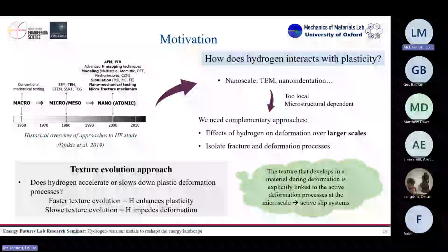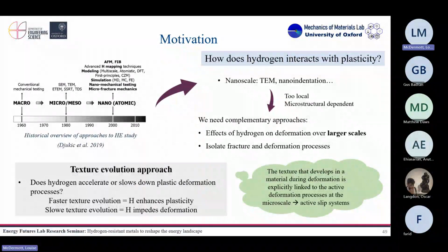So what we could say is, okay, if we observe faster texture evolution in the samples that have hydrogen, then it means that hydrogen is enhancing plasticity. Okay, it's fostering dislocation motion, and basically sliding of dislocations on the slip systems. Then if we saw a slow texture evolution, then hydrogen is pinning my microstructure and hindering deformation.